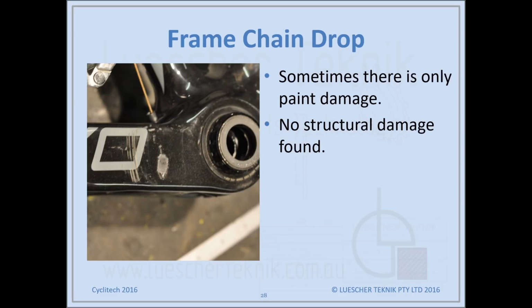Another case of chain drop, and in this case, there was some visual surface damage to the paint. However, the scan revealed that there was no underlying structural damage. So again, you could do a paint repair just to seal the surface again, and no underlying structural damage was noted.